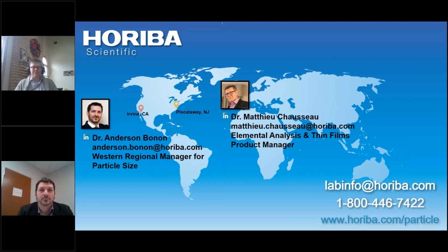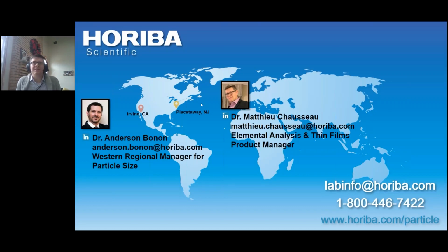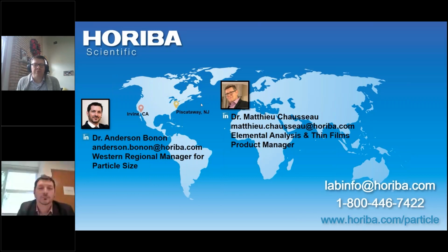So, energy dispersive XRF versus wavelength dispersive XRF, which kind of setup is recommended for stainless steel powders? Well, if you look at the ASTM list, most likely WD-XRF will be mentioned. All experiments here were made using ED-XRF. The benefit you can have with WD-XRF is the resolution. It's higher resolution than ED-XRF, meaning that you will be able to better detect low concentration elements in the matrix and have a better detection limit.